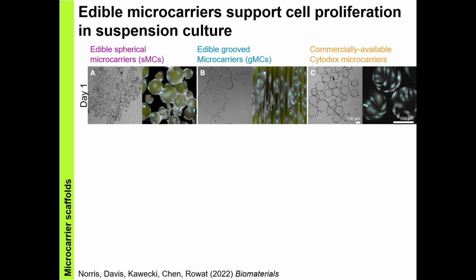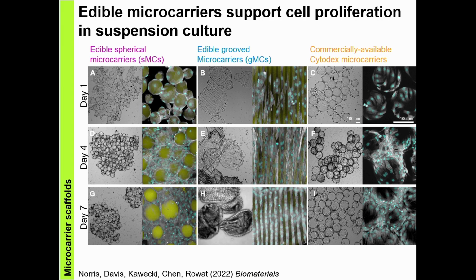So the first question is, how do the cells interact with these microcarriers? We can see both on the spherical and also the grooved microcarriers, compared to Cytodex microcarriers, that the cells are indeed adhering. You can see the nuclei labeled here in cyan, F-actin in white, and the beads are yellow. And we see over time that the number of cells tends to increase, which you can see by the increase in the number of cyan-colored dots or nuclei over time. And we see increased growth in all three situations.